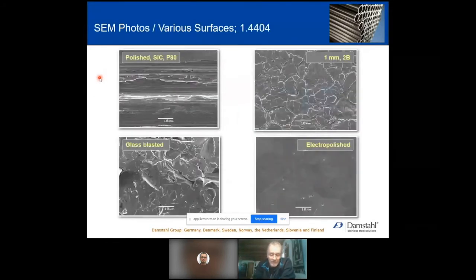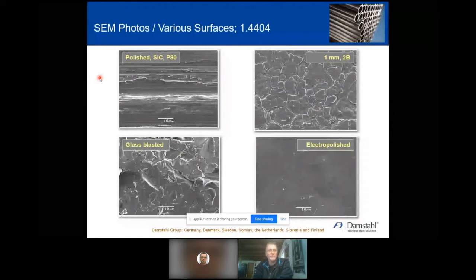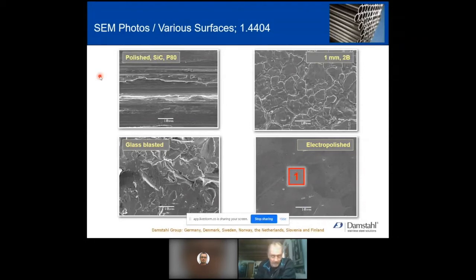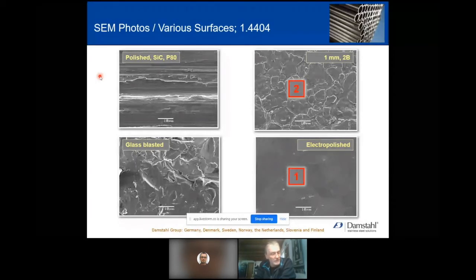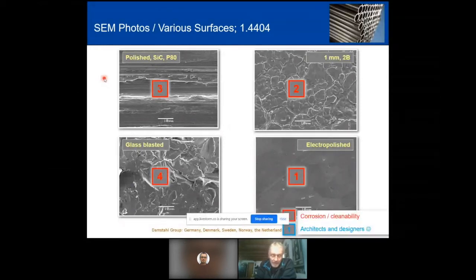If we take a look at the electron microscopy photos of various surfaces, then we have the electro-polished. I completely agree with Dr. Herzl, this is the perfect surface treatment, but also the 2B, the cold rolled surface we get from the mill, is actually quite good. Third best is probably the polished, and the glass blasted is the worst. Unfortunately, the world has invented people who are not engineers, the architects and designers, and they will definitely say that the glass blasted is the best, and then the polished and perhaps the electro-polished instead of the 2B. So this is really a conflict of interest.